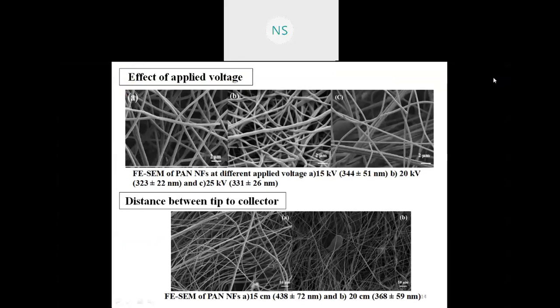Means a very low voltage can give a high size, and a very high voltage can also give a high size, but it is lower as compared to the very low voltage, that is 15. When we compare, 15 kilovolt gives 350 nanometer size of the fiber, but 25 kilovolt gives 330 nanometer size of the PAN nanofiber. But in the moderate case, when we go with 20 kilovolt, it gives a very low size as compared to 15 kilovolt as well as 25 kilovolt.